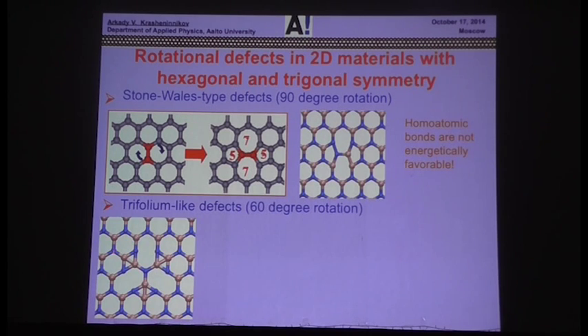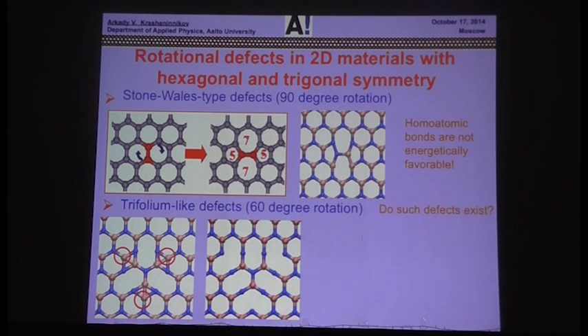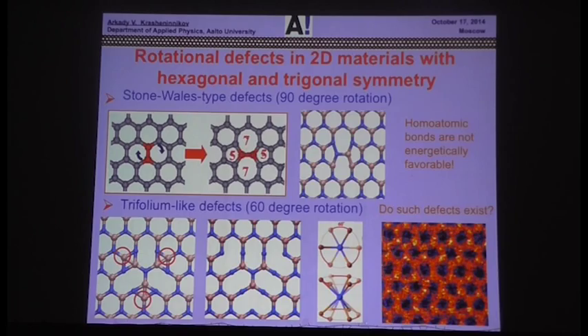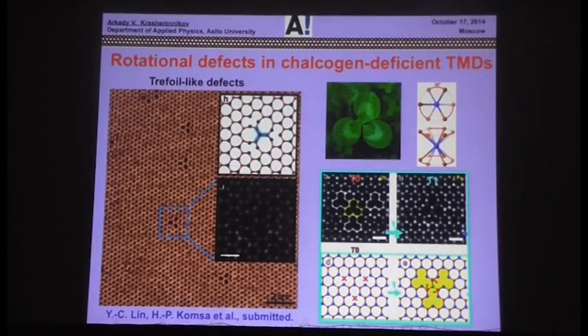Well, the density of atoms may be a bit too high here, but if you remove the atoms, the structure may be quite stable. In dichalcogenides, you should actually rotate like 6 atoms, like that. And in fact, if you look at TEM images of tungsten diselenide, at some point you will find the signature of these very interesting trefoil-like defects. Basically, this is what, again, our co-workers found in several transition metal dichalcogenides. The structure is chalcogen deficient. Six atoms are missing in this case, and then you can rotate this unit by 60 degrees. And energy will go down, as follows from our calculations.